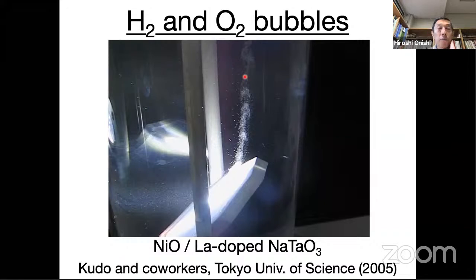And these bubbles are hydrogen and oxygen mixed gas bubbles. So 20 years ago, they provided a good photocatalyst to make hydrogen and oxygen bubbles by using photocatalytic water splitting. This demonstrated that their photocatalysts are very efficient for this reaction.